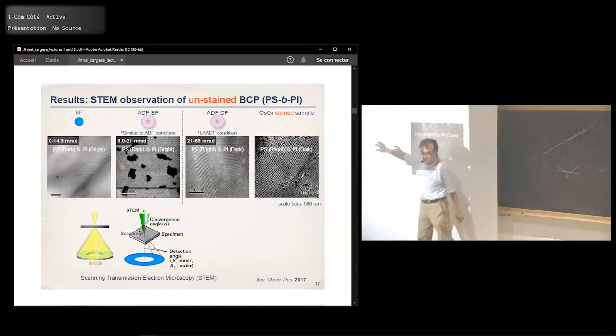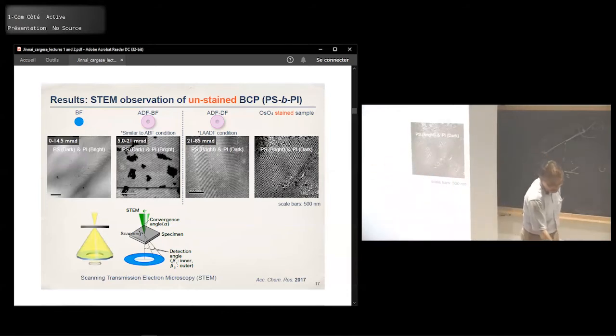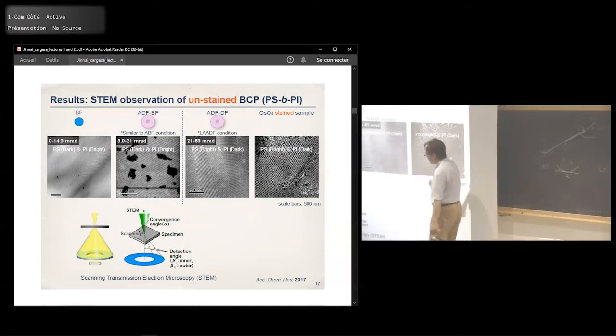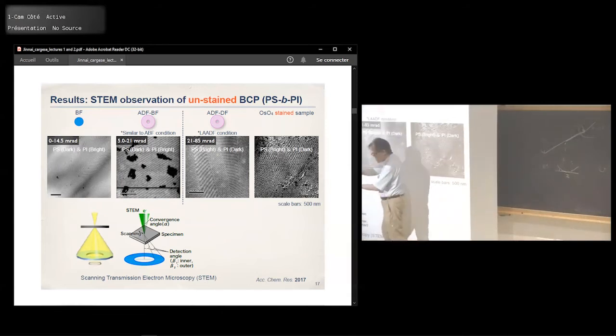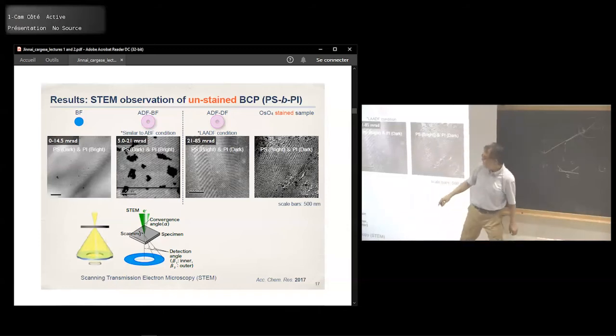So you start to see some structure, and then you can use this donut type of structure of a detector, and by changing the camera length, you can change the scattering angle. Okay, this is the inner angle, this is the outer angle. Inner and outer, so these two have a detector at a different camera position. Okay. Anyway, you have a nice contrast.